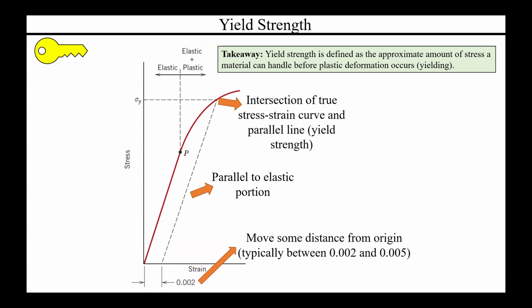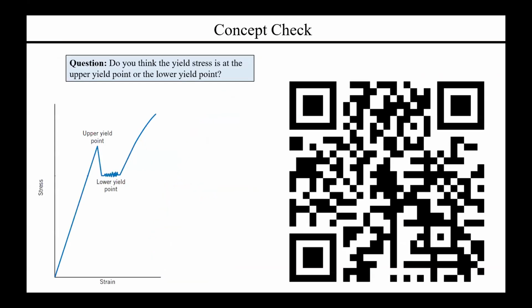And one way to estimate this yield strength is, you take a strain of around 0.002 to 0.005, and you draw a line that has the same slope as your elastic region. Where it intersects your stress-strain curve is a rough estimate of what your actual yield strength would be.